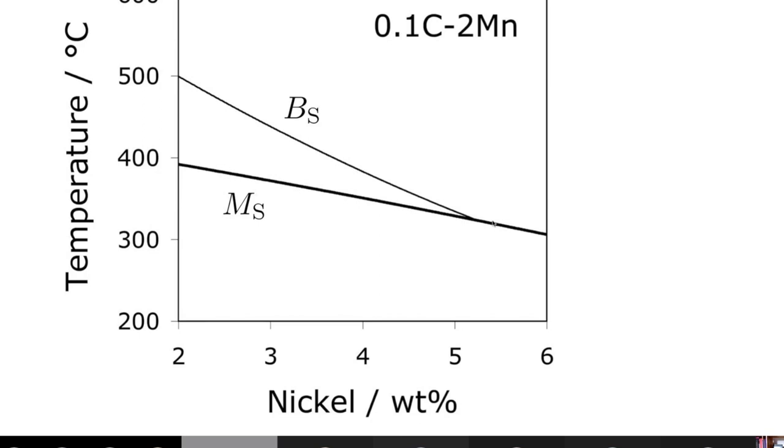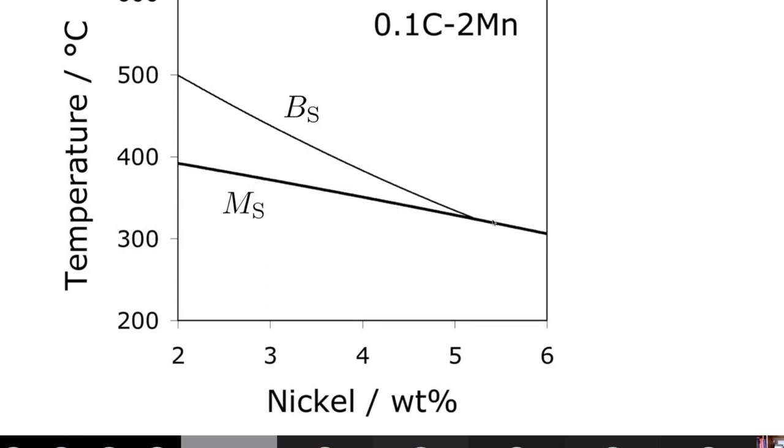So for this specific alloy system, you can find this on my website if you look for Hong Seok Yang and Bhadeshia. So the idea that all three phases form in all alloys is not actually correct. It depends on the specific driving force for your alloy. If the driving force is very small, you will only get martensite. So for example, for an iron 30 nickel alloy, you do not get anything except martensite.